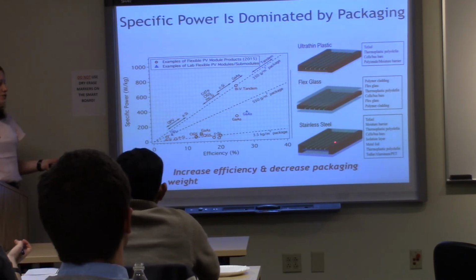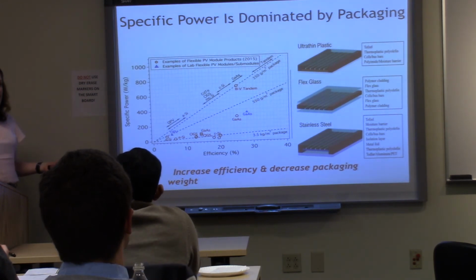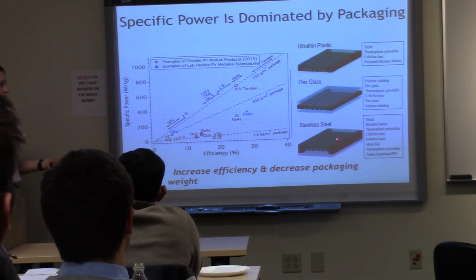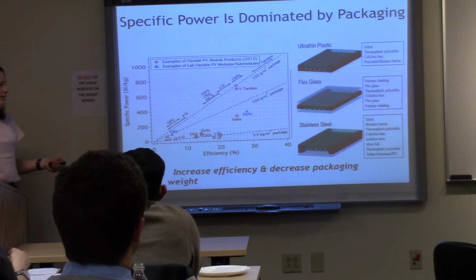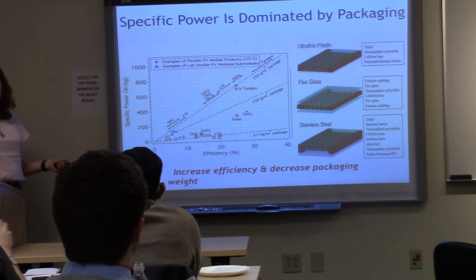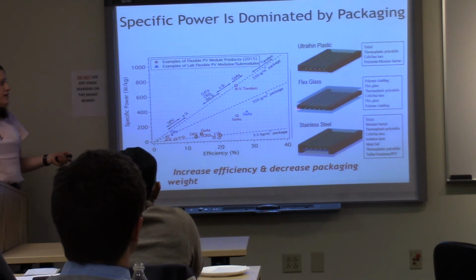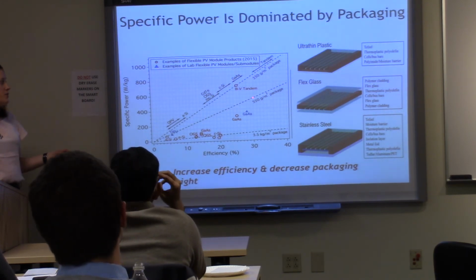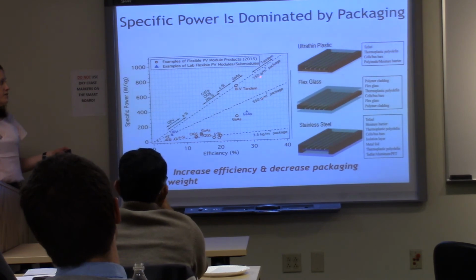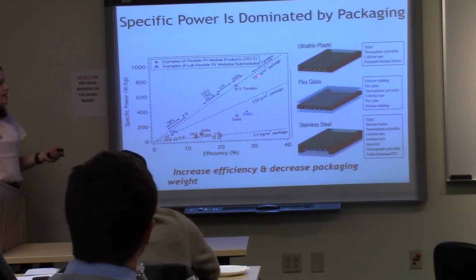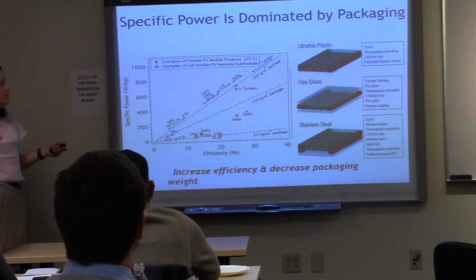If you're on a stainless foil, in order to be thick enough to have good mechanical integrity, you're inherently going to be kind of heavy. If you're on a 3.3 millimeter slab of glass, that's going to be really heavy. If you can go to this 100 micron thick flex glass, we're pretty sure we can get to 350 grams per meter squared of packaging, which would help us get to our specific power targets.